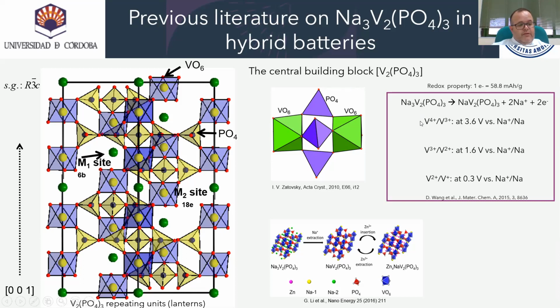The redox property of this material allows to get around 60 mAh per gram per 1 electron. And the potential reactions at 3.6, 1.6, and 0.3 volts have been assigned to different redox couples when cycled in zinc and sodium cells.